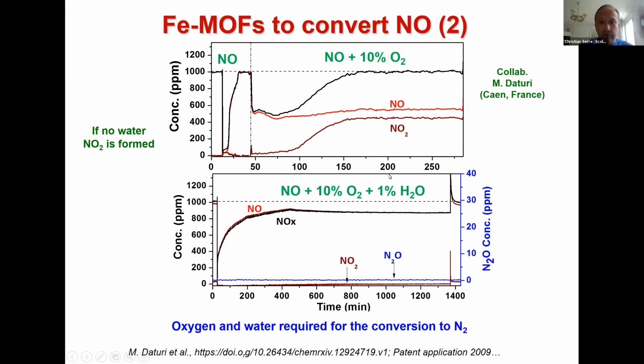As soon as you start to introduce water, then you have this catalytic transformation of part of the NO into N2, and the concentration of NO2 is much smaller. So it means that oxygen and water are both required for the conversion.